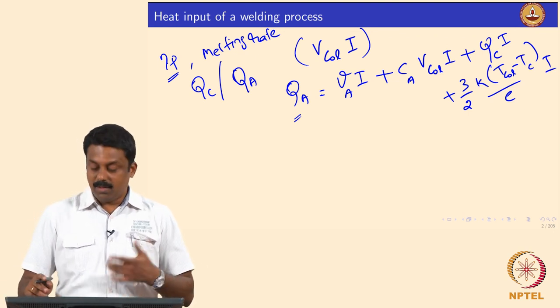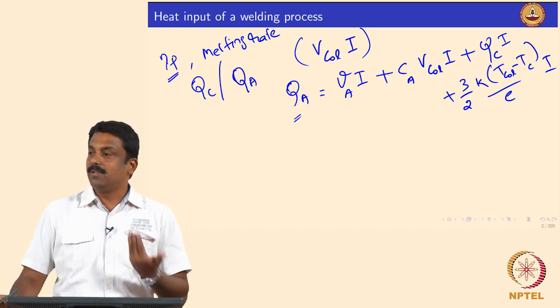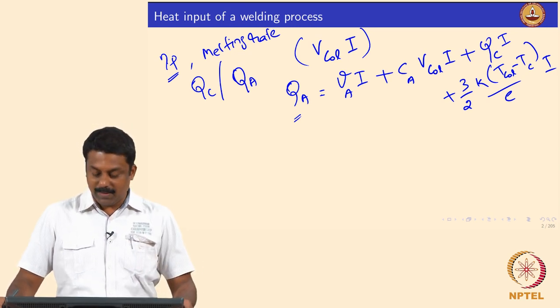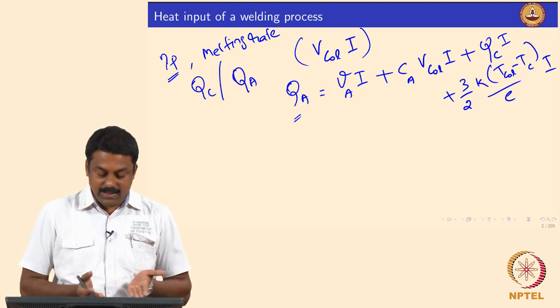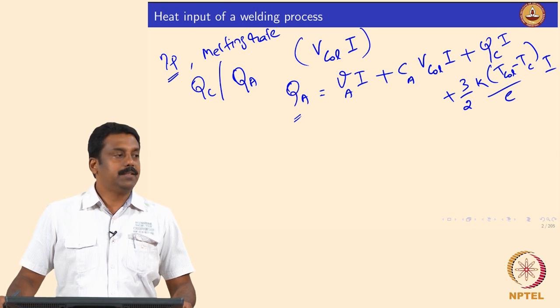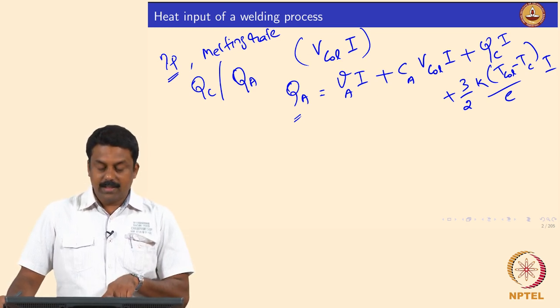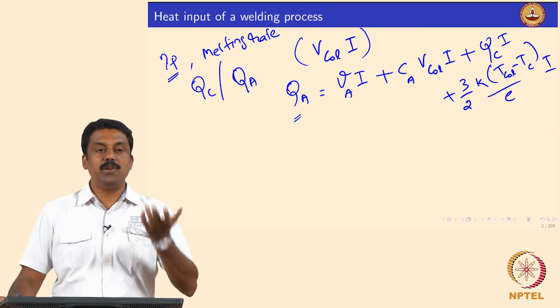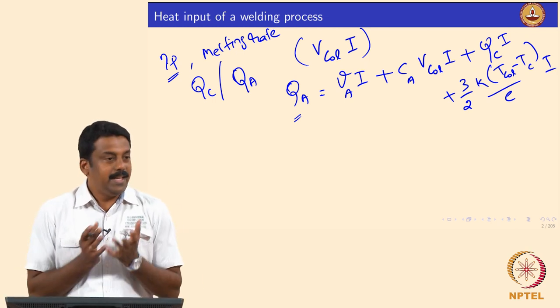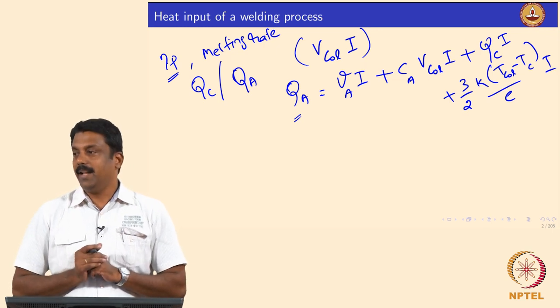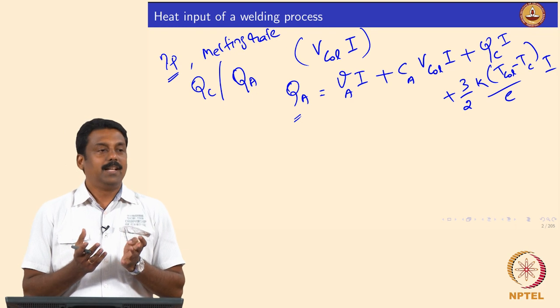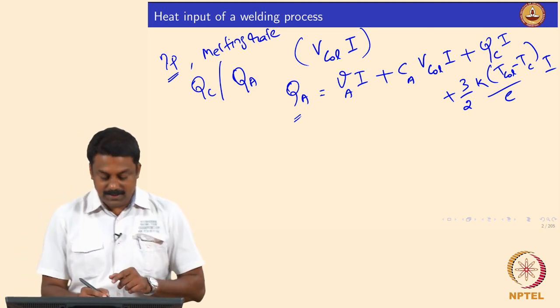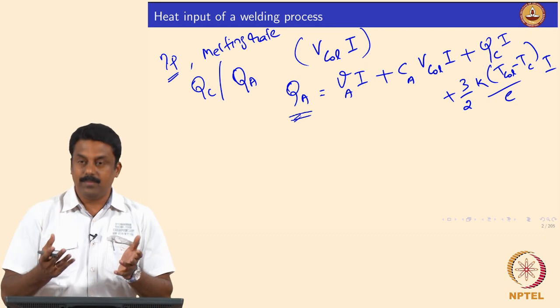All these are positive terms in the anode — that is why the temperature is always higher in the anode. In the cathode, we have minus terms where the work function is spent and electrons absorb heat as they are heated to the arc column temperature. So now this is the heat available in the anode and cathode. The main heat available for the droplet to melt is QA if the consumable electrode is the anode, and we also have additional heat from resistance heating.